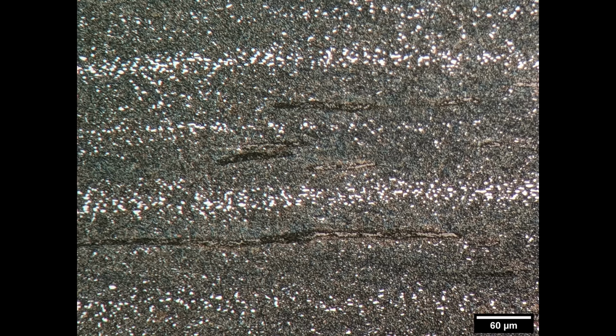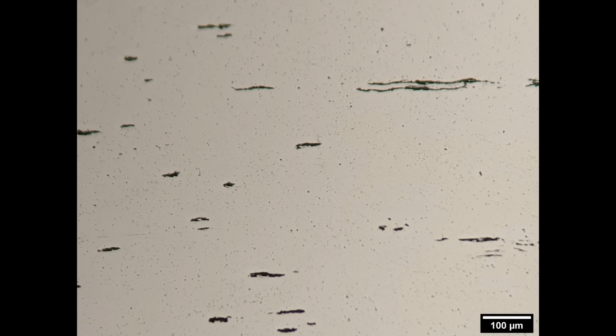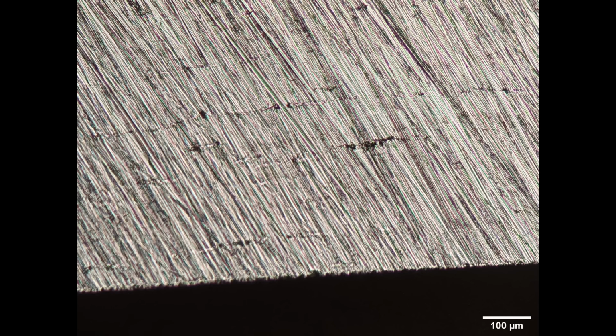One way to look at the impurities without the rest of the microstructure is to look at the steel as polished rather than etched. And when we looked at it as polished, you can see these black elongated features and also the black dots in the micrograph. Those are all of the impurities or inclusions. And there were enough of them where we could even see them in the sharpened edge under magnification. So again, we've got these black elongated features, and those are inclusions in the steel. They are very, very tiny, but they do affect our overall properties as they are brittle.